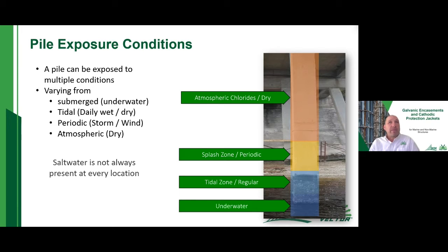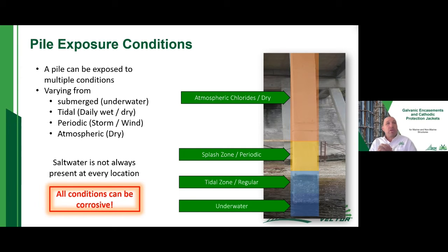One thing to think of is that even if the pile is not exposed directly to water, it still can experience corrosion even higher up in these dry or atmospheric areas. So basically everywhere on this pile, corrosion can occur. The most extreme portions are going to be the tidal zone and that splash zone right in the middle of the pile, where you have a lot of chlorides and it's wet all of the time.